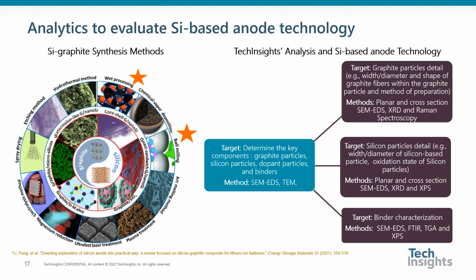The answer is not easy, but we can say it mainly depends on the silicon and graphite source plus the desired silicon ratio. At TechInsight, we performed several analyses to characterize the silicon-based technology. These analyses are focused on the graphite particles, such as width, diameter, and shape of the graphite, using planar and cross-section SEM and EDS tests, XRD, and Raman spectroscopy. We also focused on the silicon particle details, for example, width and diameters of the silicon-based particles, and the oxidation states of the silicon particles using XPS, using planar and cross-section SEM EDS analysis plus XRD. Also the binder characterization using SEM-EDS, FTIR, TGA, and XPS. By gathering this information, we could also comment on the synthesis strategy, such as ball milling and wet processing.